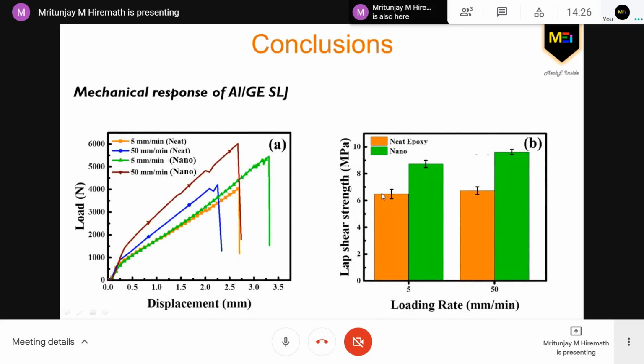So coming back to the mechanical response of the single lap joint, specifically for the aluminium and the glass epoxy, how the bond quality is being exhibited by the neat epoxy adhesive and the adhesive wherein the nanofillers are being used. So the nanofiller embedded epoxy exhibits a higher load carrying capacity compared to the neat epoxy. Therefore,